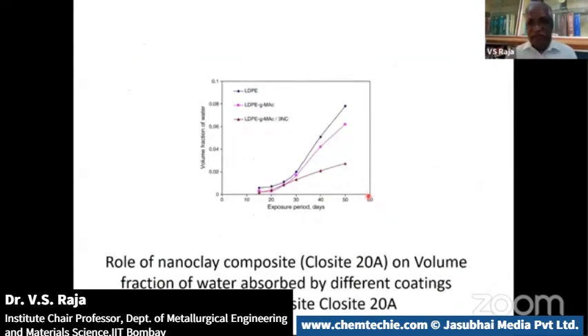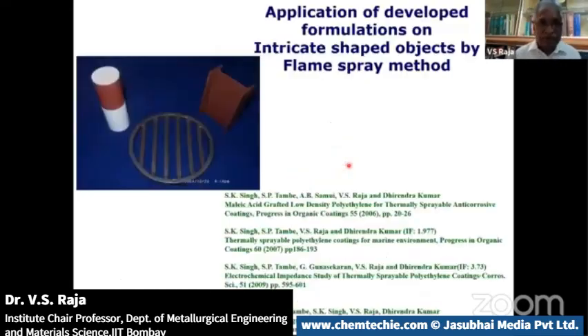A very interesting thing is that the kind of pigment that you add plays an important role. I think one of the distinguished panel members talked about nano, right? These nano pigments are very important. We just looked at the role of a nano clay composite, Cloisite 20A, right? It's a clay, actually. When you add this clay, you look at the water absorption. Look at this y-axis, volume of water absorption versus exposure days. This gives you the lowest amount of water absorption here. That is due to the addition of the clay. The clay addition reduces the water absorption and so improves the performance of the coatings.